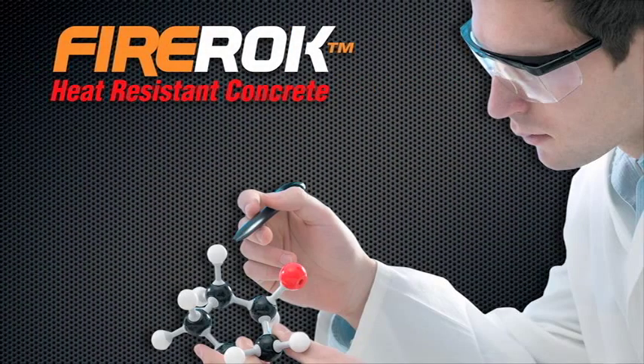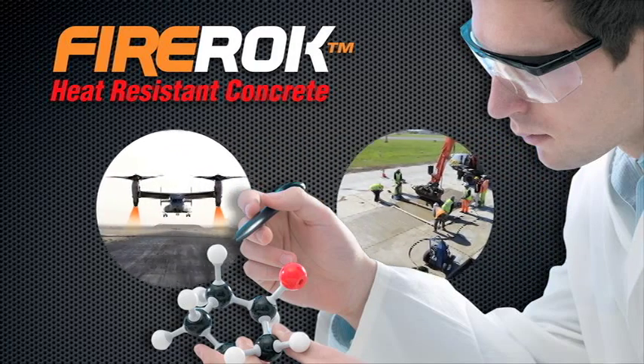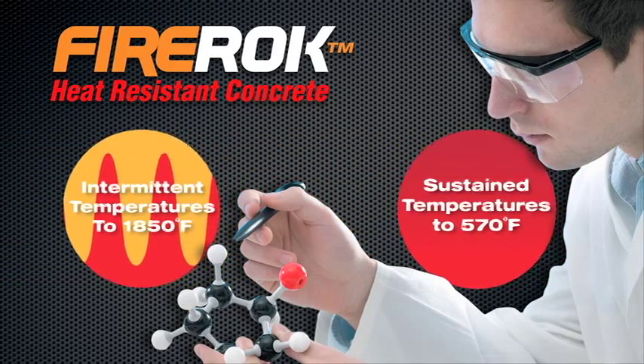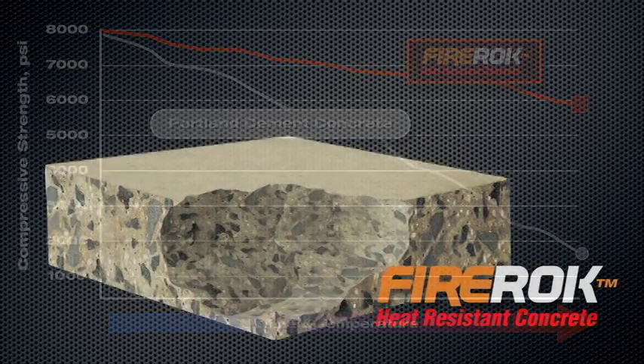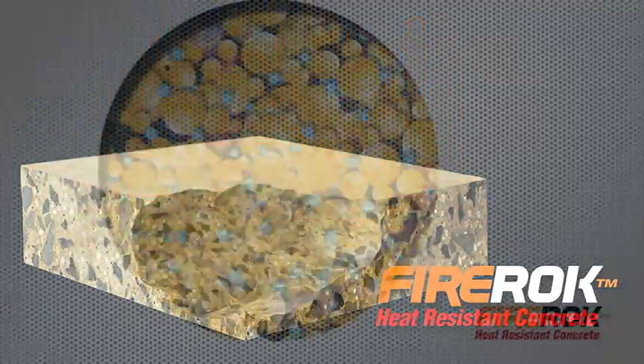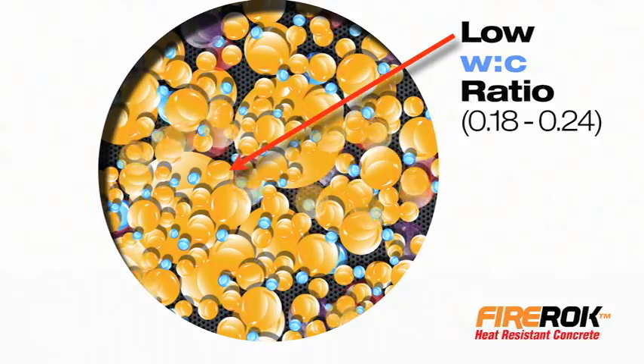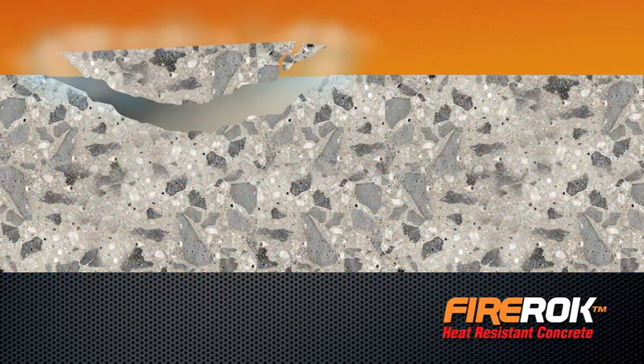CeraTech's FIREROK cement concrete has been engineered to produce a concrete with superior durability in environments subject to frequent thermal cycling and high temperatures. FIREROK can withstand intermittent temperatures as high as 1,850 degrees Fahrenheit and sustained temperatures up to 570 degrees Fahrenheit without significant loss of strength. FIREROK produces an extremely dense concrete with high thermal diffusivity rates to enable it to withstand high intermittent thermal loading. Its spherical cement particles also reduce yield stress and viscosity during mixing and allow for low water-to-cement ratio mix designs. The majority of mixed water is consumed in the hydration process, leaving negligible free water to facilitate steam spalling.